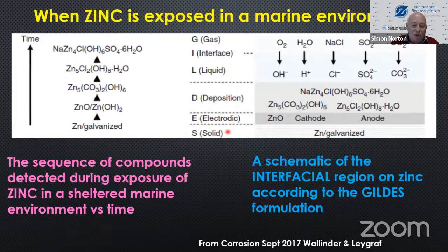On the right-hand side is a model that was developed by GILDES, and it's quite a useful model in that you've got a solid zinc coating, zinc-rich paint or zinc thermal spray. You've got anodes and cathodes on the surface, and this is called the electrodic area. And then slowly, with time, these compounds that I showed you on the left start to deposit on the surface. And how do they form? Well, the atmosphere is the gas. There's an interface with the liquid, say the seawater, and you get oxygen from the atmosphere, water from the sea, sodium chloride from the sea, sulfur dioxide from the sea, and carbon dioxide from the atmosphere. And all of these together form a very complex deposit on the surface of your zinc. And this deposit is what determines what happens to your zinc when you expose it to the atmosphere.